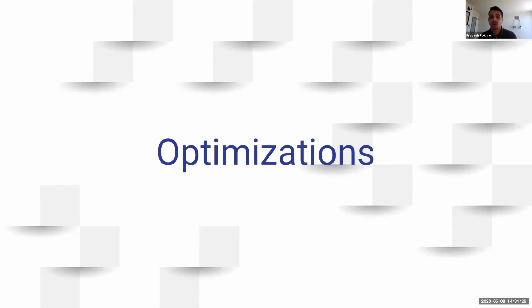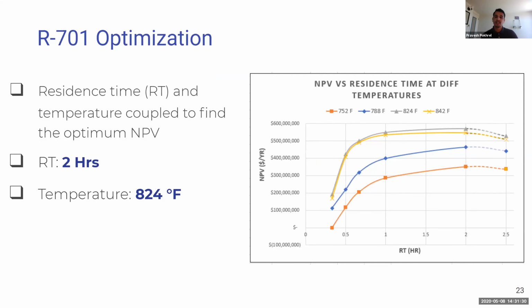Next, we're going to be talking about the optimization. The first optimization we did was reactor optimization. We used reactor residence time and the temperature coupled together to find the optimal NPV value. As you can see, our optimal NPV value was around 2 hours of residence time at 824 degrees Fahrenheit. It was the second highest temperature where we got our optimal NPV.